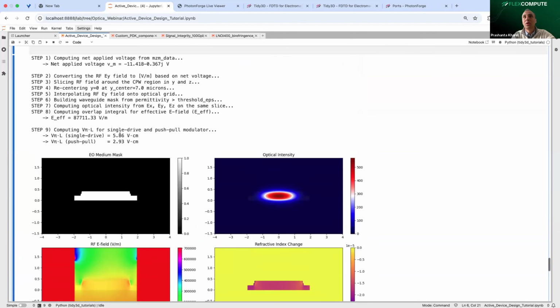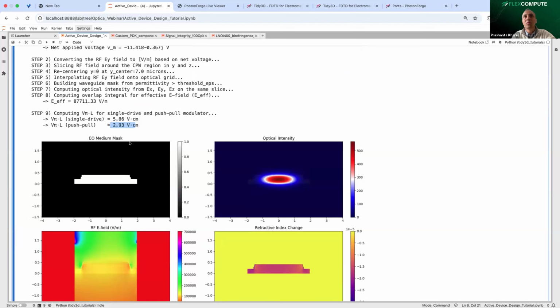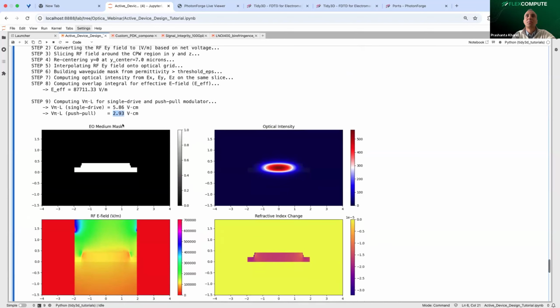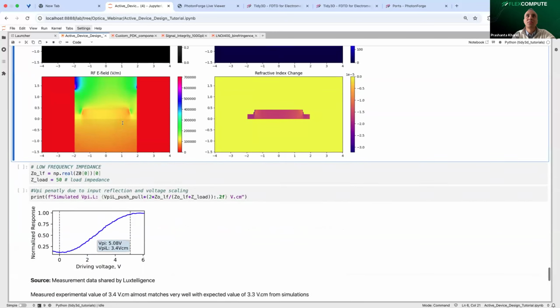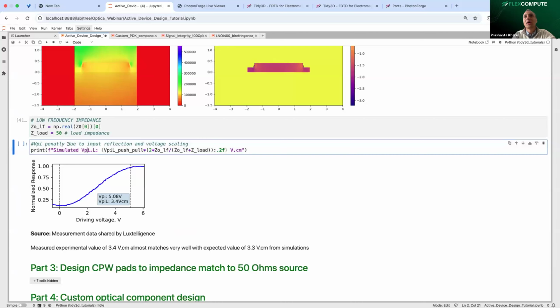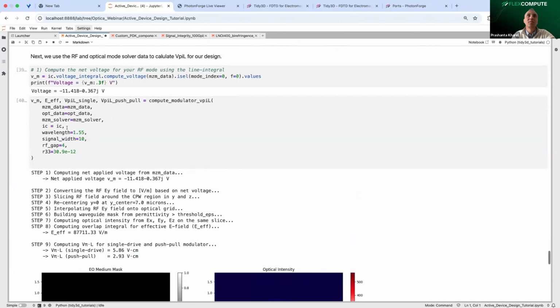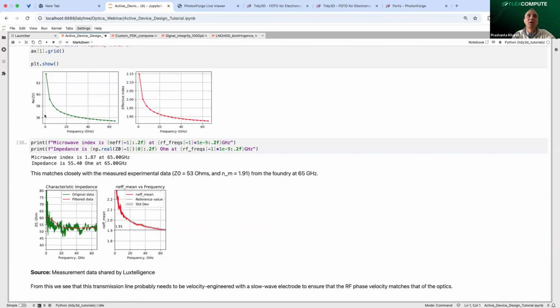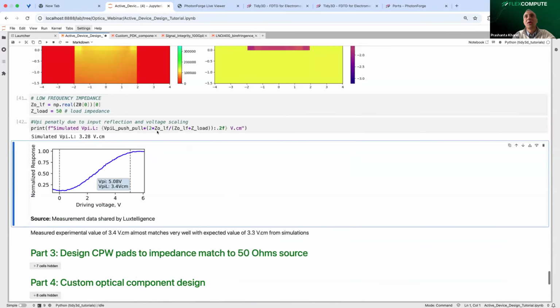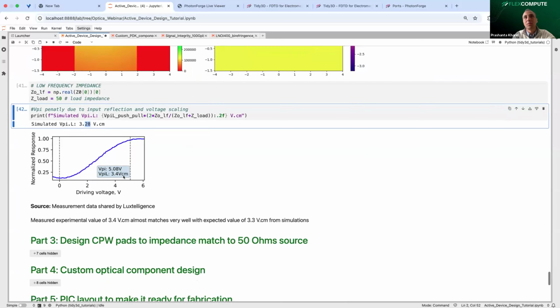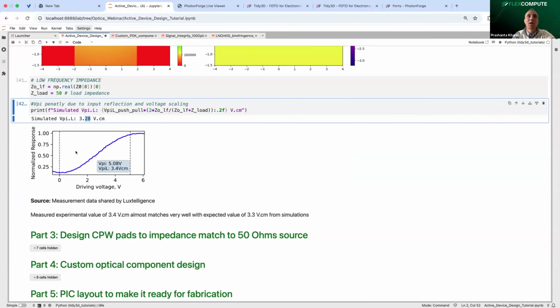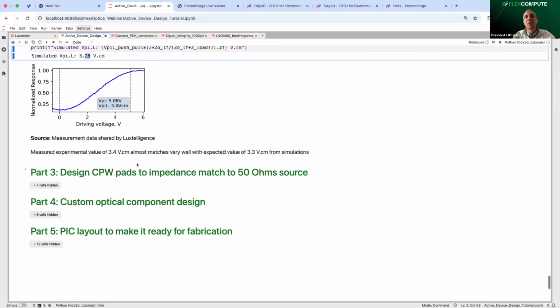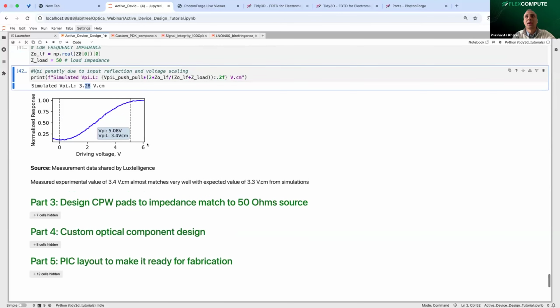From the simulations, from doing this electro-optic overlap, we see that the V-pi-L for push-pull configuration in an MZM is around 2.9 volts per centimeter. But we do need to account for the input reflections and also do the voltage scaling, because the impedance, as we saw, close to 1 gigahertz is not 50 ohms. It's a little bit higher than that. Once we take that into account, we see that the simulated V-pi-L is close to 3.3. This is measured data from Luxtelligence, and they measure that the V-pi-L is around 3.4 volts centimeter. So there's also a great agreement between simulation and measurements.